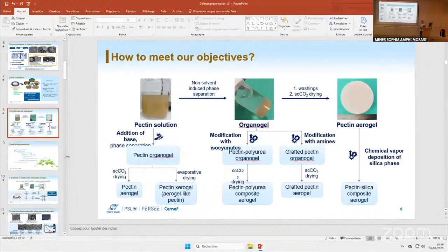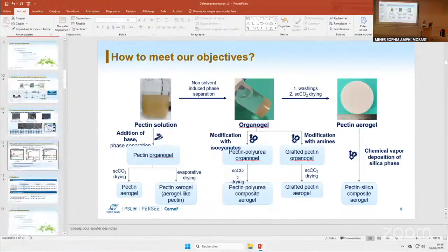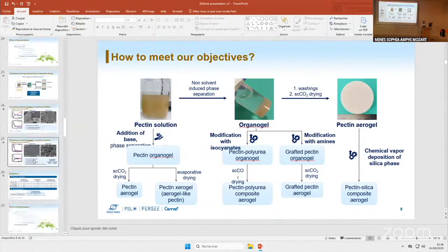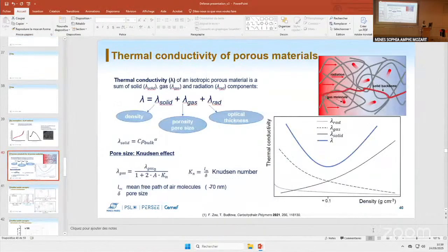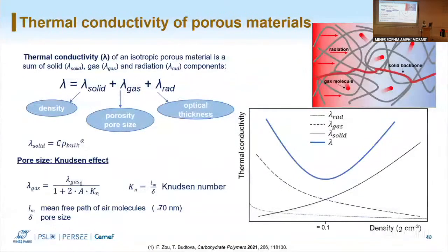Okay, a question about the transfer mode for heat. So you have shown, I think it's page 63 of your manuscript, a scheme of principle on how heat is transferred from one side to another of your material. I seem to remember that on those materials, you also have the effect of dangling chains, which is not taken into account yet. Dangling chains, so chains that are not connected to each other. That's actually beneficial to the fact that you don't transmit heat, because those chains stop a little bit the heat from being transmitted. I was a bit surprised that you didn't consider that effect in your materials. Maybe it's just because all chains are indeed connected to each other. So do you have any means to check that? Especially given that if you compress, you also see effects. So what do you think about it?